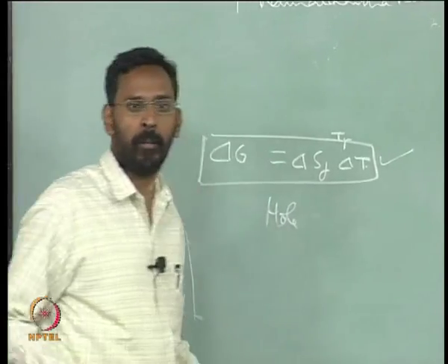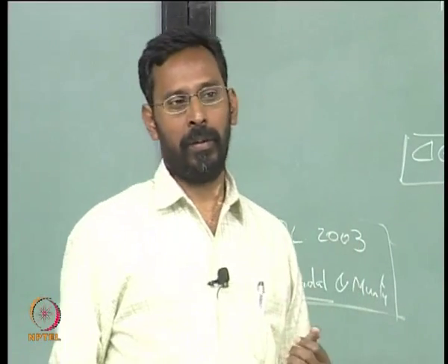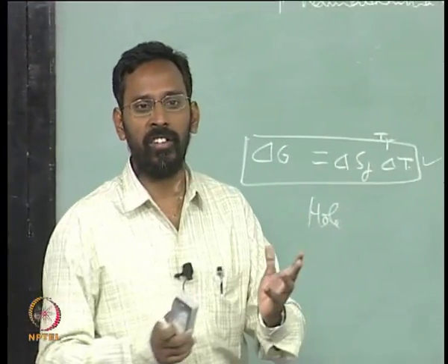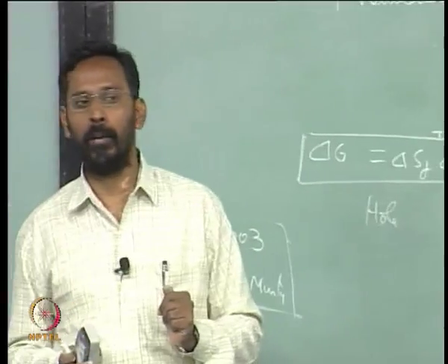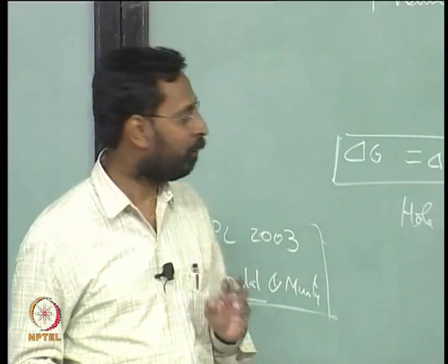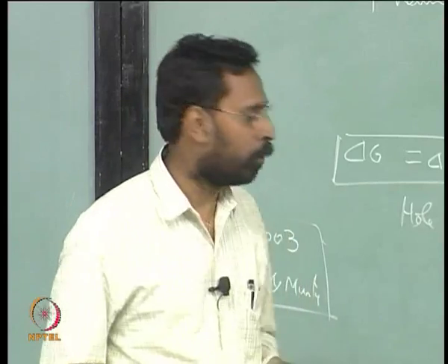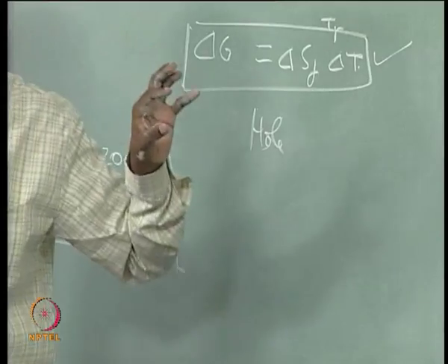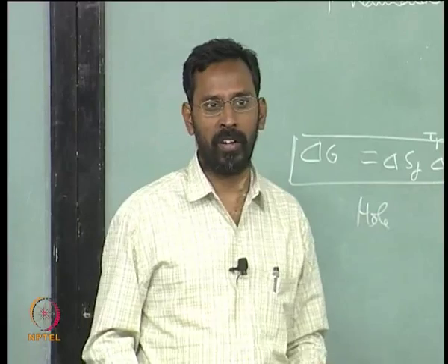Assume that liquids are composed of free volume, that there are always certain holes, because definitely there is much more free volume in a liquid than in a solid. A solid has a definite crystalline structure, I am talking about crystalline solids only, where you talk about tetrahedral voids and octahedral voids. Whereas in a liquid you have much bigger voids, and that is what hole theory talks about. And from that they tried to derive what would be the Cp of a liquid at various temperatures,